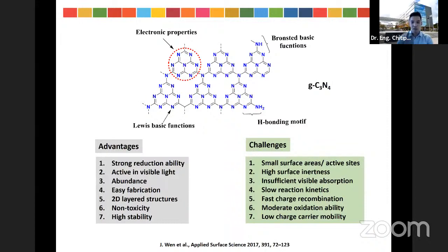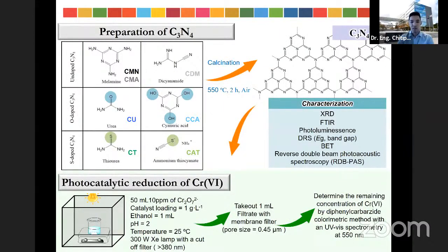And the main problem of this material is the recombination of the electron-hole pair, which reduces the photocatalytic activity. So in this work, we doped oxygen or sulfur by calcining melamine with the co-precursor as shown in this table. And we successfully prepared the doped samples, as shown by XRD and FTIR, and we applied this material for chromium reduction.